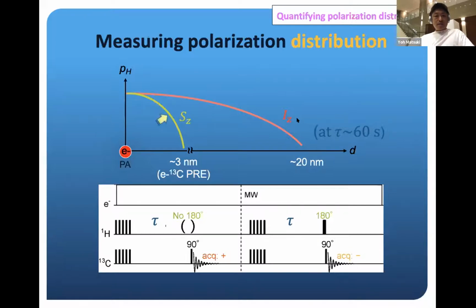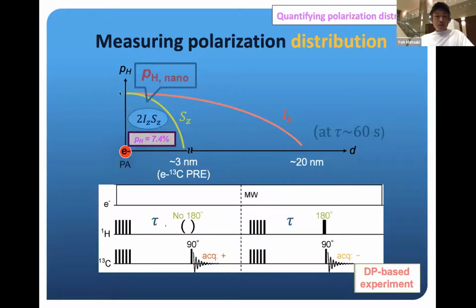But the exception is the carbon, which is experiencing PRE from the electrons within 2 or 3 nanometers from the electrons. That comes up much faster, in the order of half a minute or so, generating this spin correlated term in the space right next to the radical molecule. And then we actually used this spin correlated term to calculate 7.4%, meaning that this particular experiment, based on this direct polarization or DP based experiment, is primarily sensing the polarization level within nanospace around radical molecule.